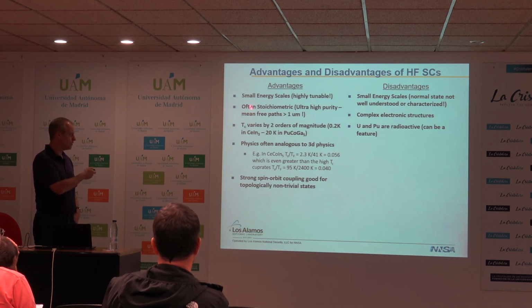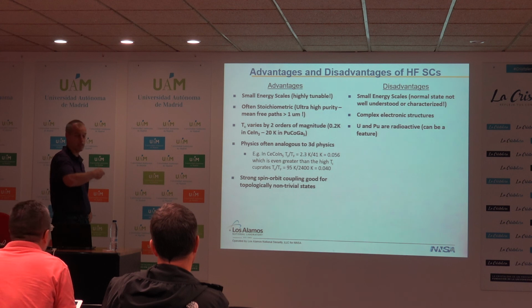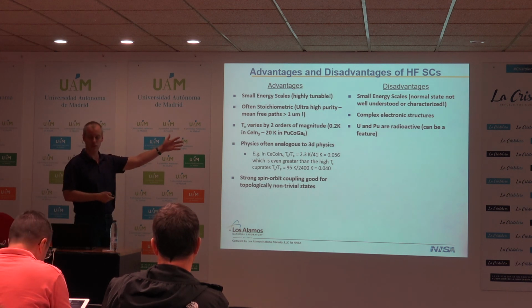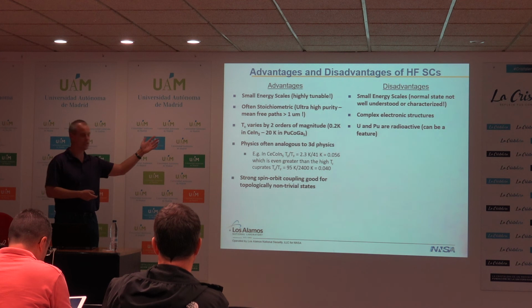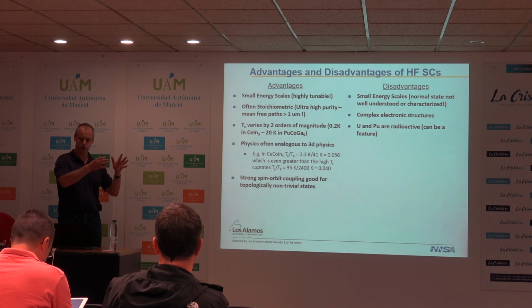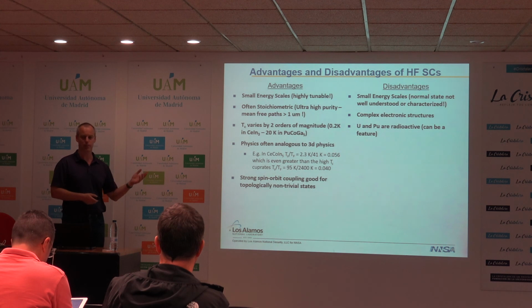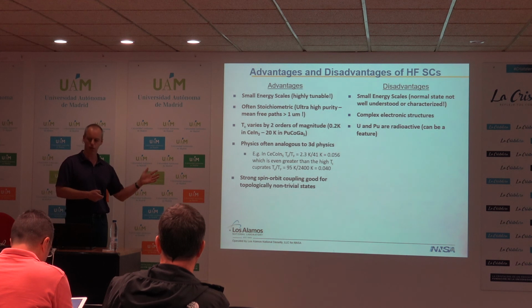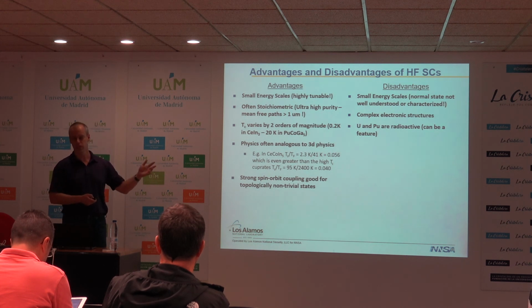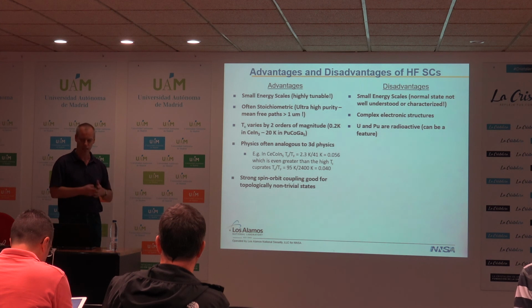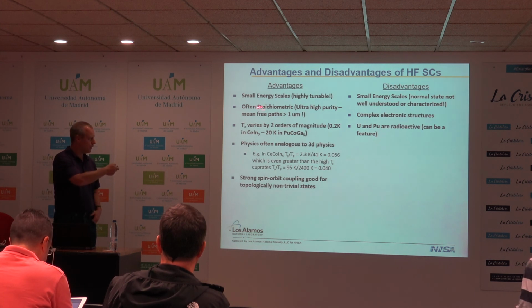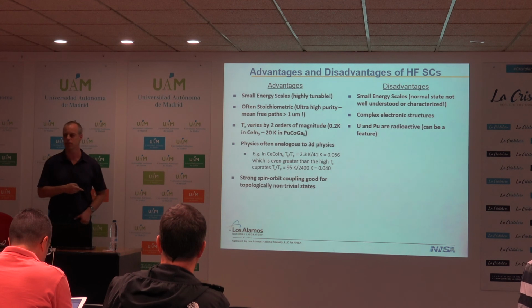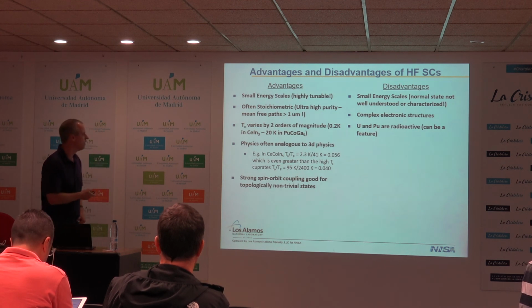However, we have stoichiometric systems. That means we have really high purity, with mean free paths greater than a micron. That's good for quantum oscillations. It also allows you to see states that you wouldn't otherwise see. So this Q phase, this pair density wave that we were mentioning in cerium cobalt indium 5, in fact disappears with less than a fraction of a percent of impurities in the system. We put in non-magnetic dopants, tin on the indium site, and it completely kills the state. So being able to see new states sometimes requires this incredible cleanliness.